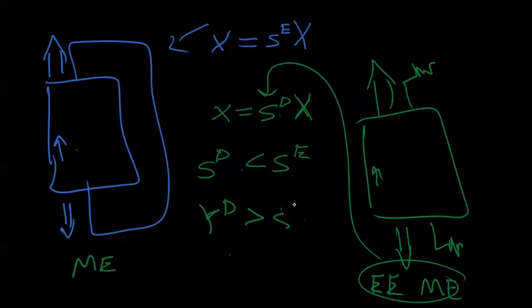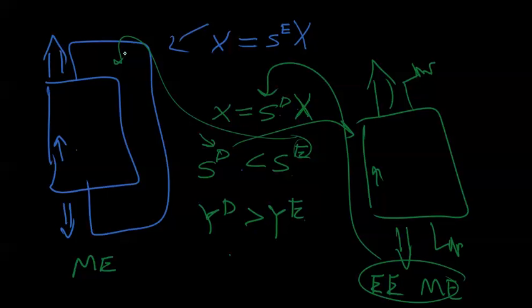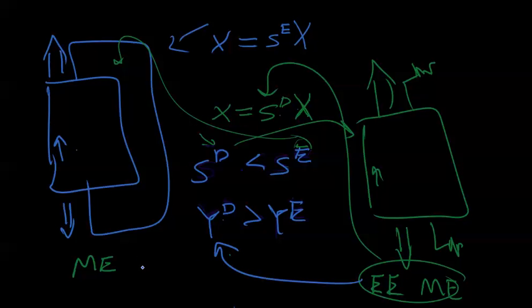The Young's modulus of YD, constant displacement, is higher. See, this is constant electric displacement, which refers to this case, and this is constant electric field, which refers to this case. So we have to really understand what is going on. One's upside down, right? Something that's more compliant is less stiff. So here we have double energy, and here we have a single energy.